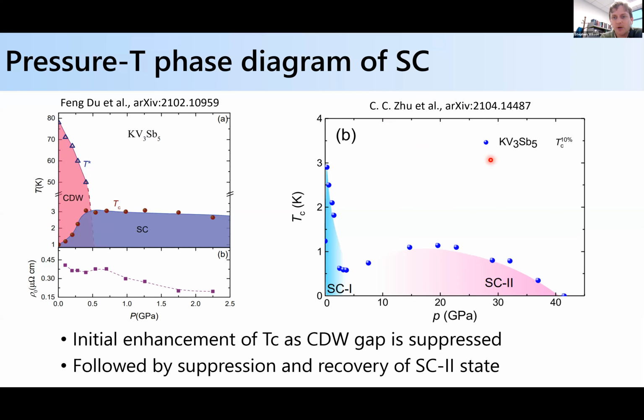But then other work looking at higher pressures, up to 40 GPa, finds that the superconductivity comes down, potentially goes away, but then comes back with a second dome at higher pressures, okay? And so there are some open questions about whether or not this superconducting phase at low pressure is the same as the superconducting phase at high pressure. And that's a subject of ongoing investigation.